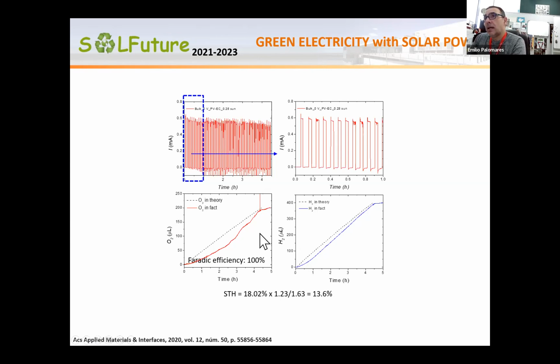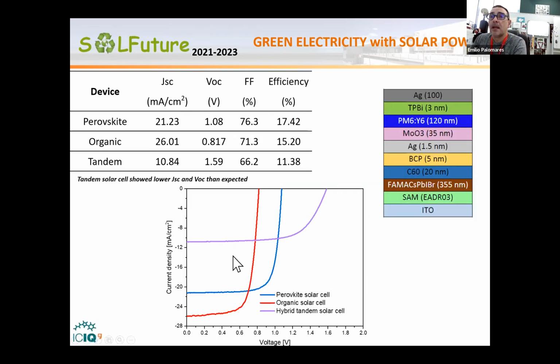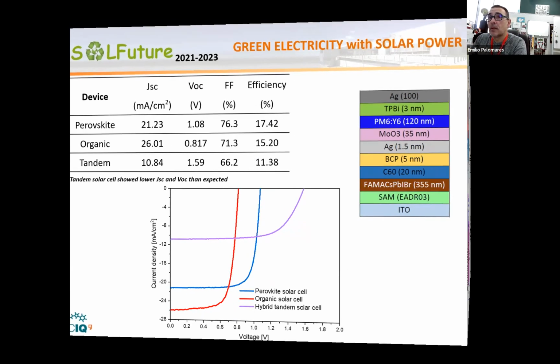But I think it's a good way to actually combine solar-driven water splitting systems with wires, of course. I mean, doing everything in one single material is much more challenging. From that, we moved towards a combination of organic solar cells, which I will not talk about today because of the lack of time, and perovskite solar cells. The idea was to combine the best of the two worlds, the organic solar cells and the perovskite, and then have enough power to do a more challenging reaction, which is the reduction of CO2.